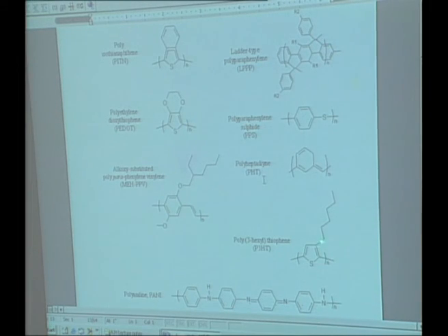Now, why does that matter? Well, if you look back at the theory of the van der Waals interactions, they come about from quantum fluctuations of the polarizability. In these pi electron systems, in these semiconducting polymers, polarizability is sufficiently large that the van der Waals interaction is so large that, in fact, they won't melt. How can we deal with that? Well, we can deal with that, for example, if the chemistry is compatible, by putting a side chain on here.